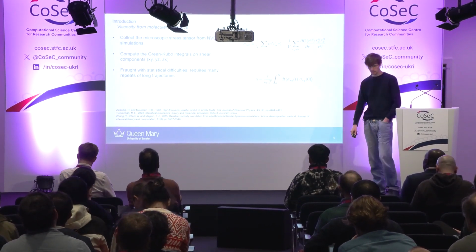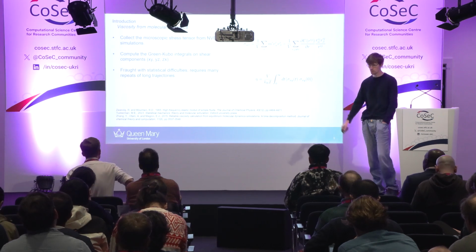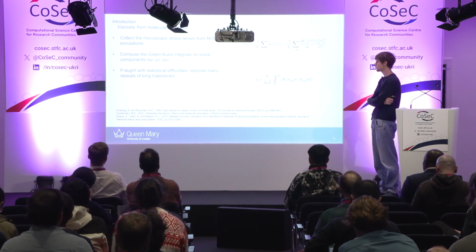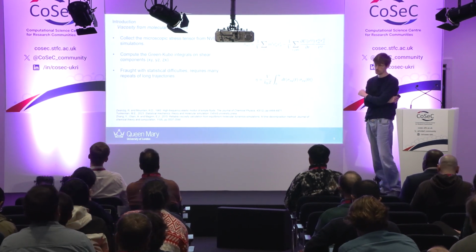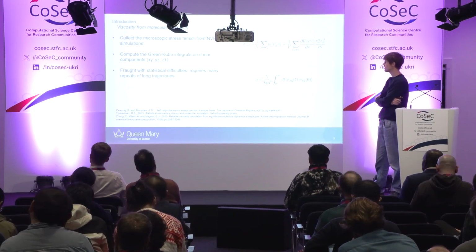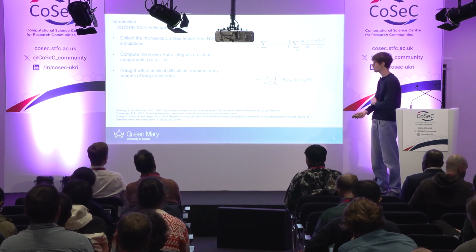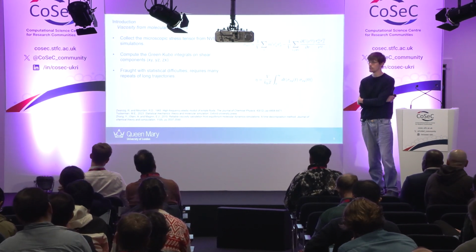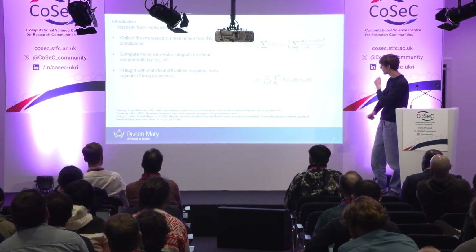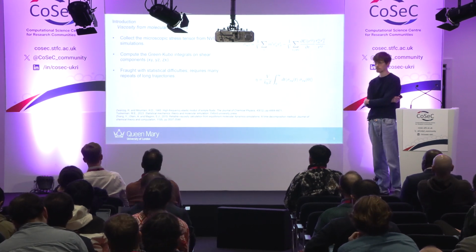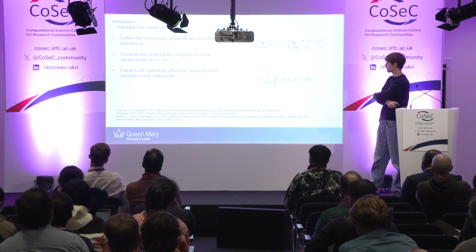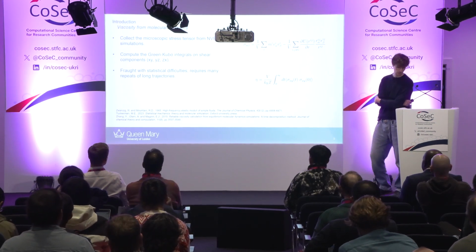So the main workhorse we have in what we're doing here is molecular dynamics. In particular, we're interested in calculating viscosity as one of the key properties of these liquids. In order to do that, you will first need to be able to calculate the microscopic stress tensor, which we can find in pretty much any MD package, and then compute the viscosity via Green-Kubo-like relations, which can be done for other transport properties as well. So in this case, we take the integral of various shear stress components of the microscopic stress tensor.